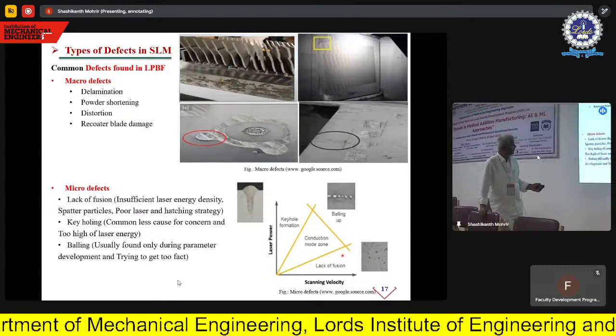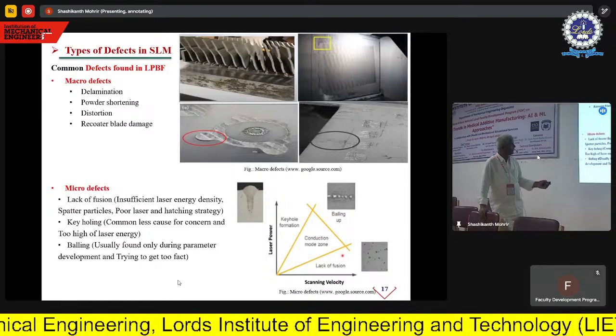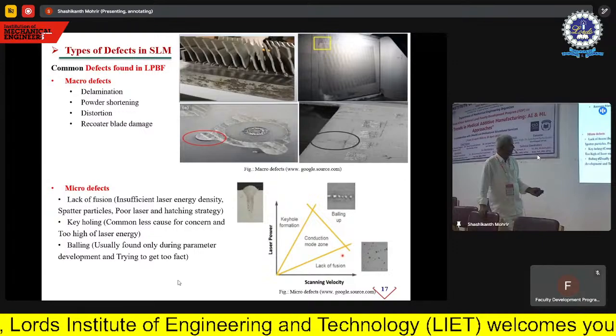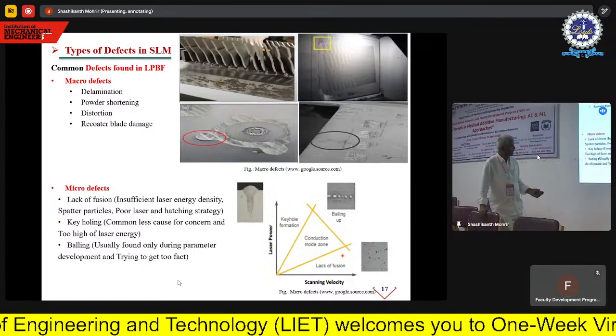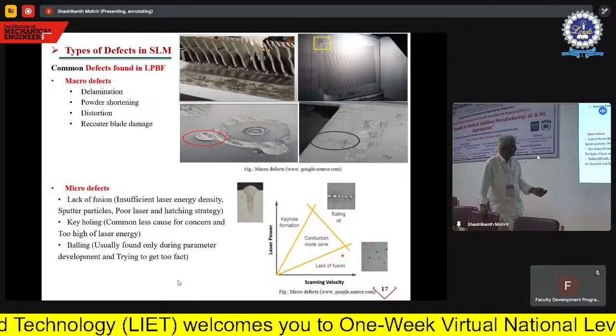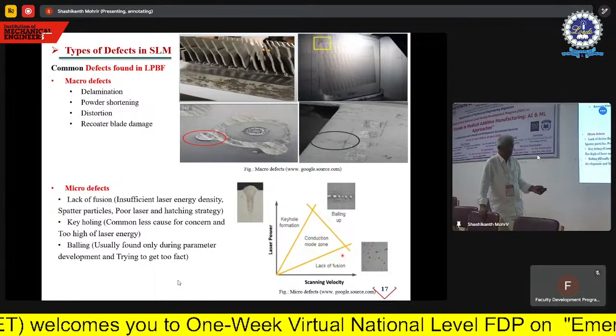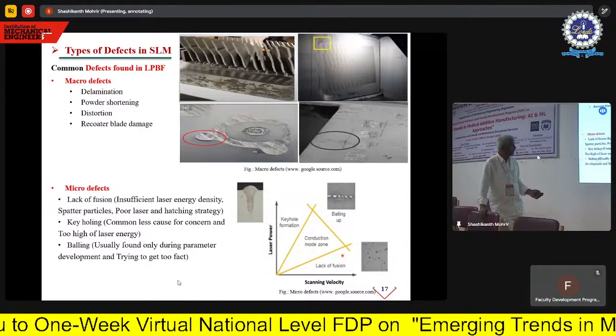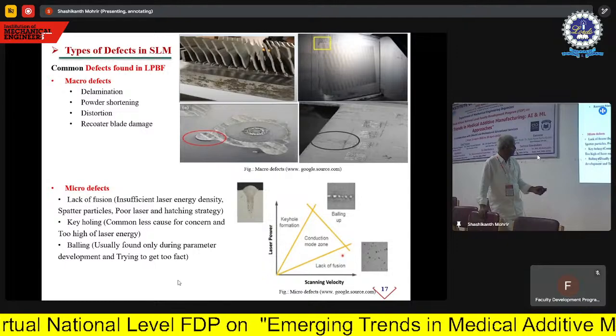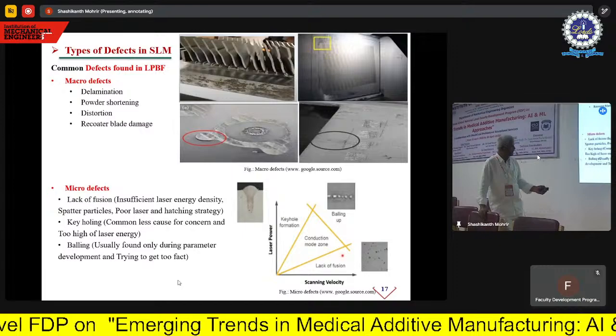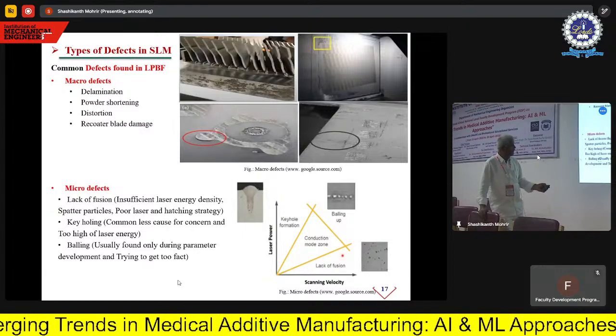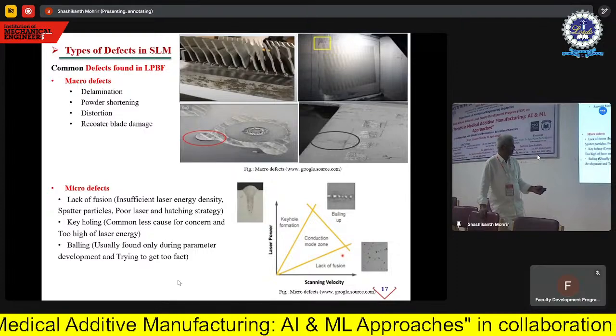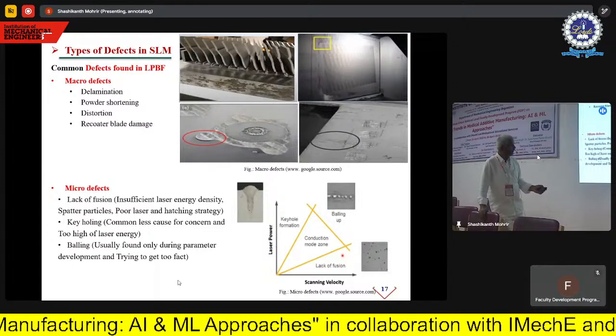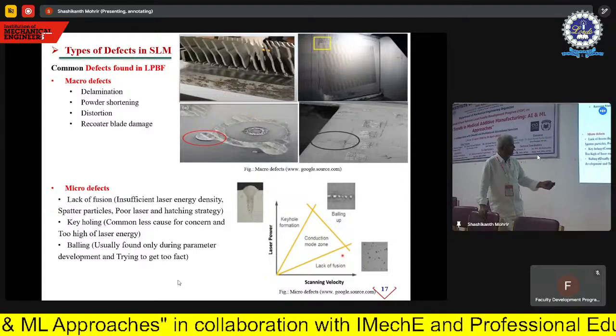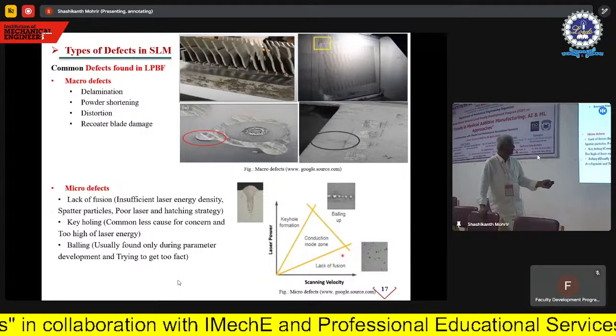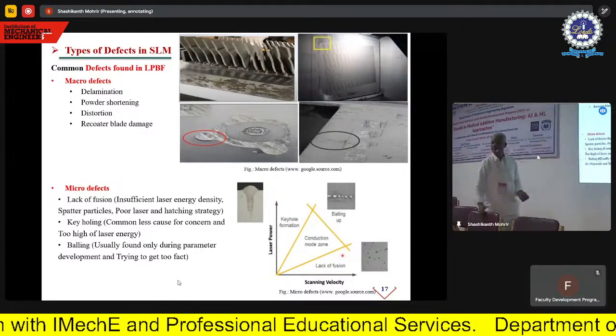Okay. So if you have a high laser power, you are going to get a keyhole like this, keyhole formation. If you have high scanning velocity, you are going to get this type of lack of fusion between the powders. But you can have scan velocity and laser power optimal along this path, straight line. You can get a good density fusion of the powder metal. And if you go beyond this one, high scan velocity and high laser power, you are going to get balls like this. You are not going to get dense parts.